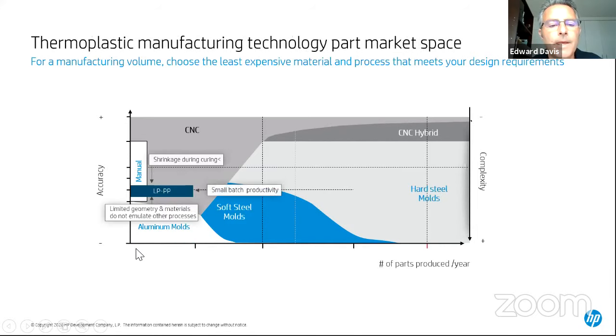Of course, the light processing, it's not a thermal process, it's a chemical process. You guys know this better than I do. Of course, you don't get differential thermals. What you get is differential shrinking. And so you get some pretty good tolerances, but you can't get great tolerances because of differential shrinkage. These tend to be made in small batches because of the singular layer batch that you can do. So it doesn't scale real well going to the right because of small batching.